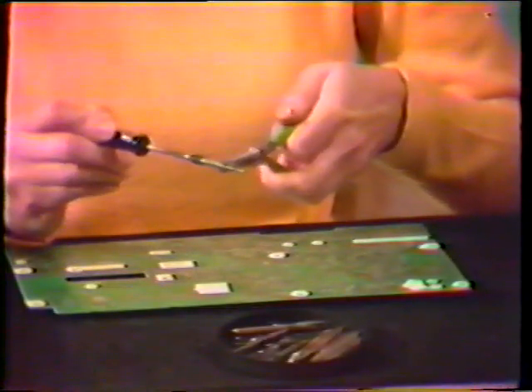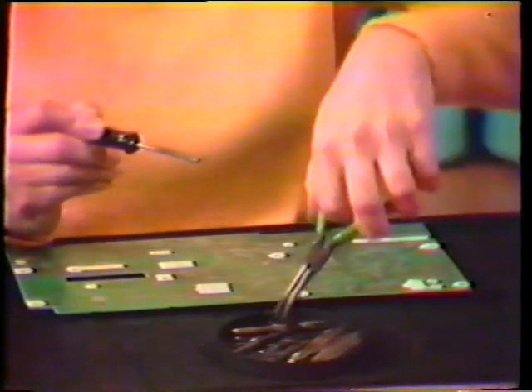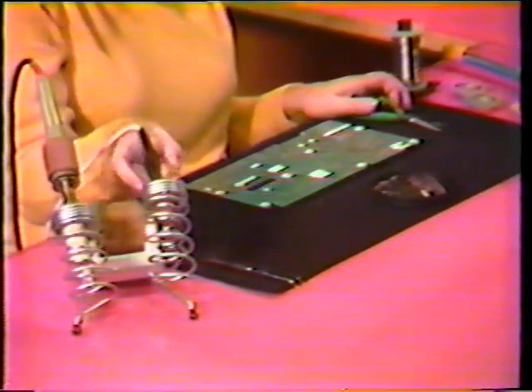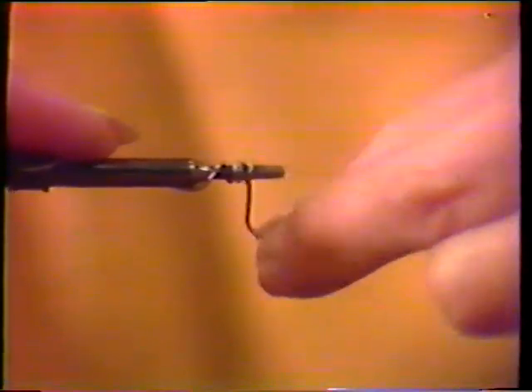But restoration can be done in a short time, either by the operator or someone designated in the assembly area. The recommended procedure is to remove the soldering tip from the hot iron and let it cool. Then, with a piece of 100 grit emery cloth obtainable from central stores, remove the scaly oxides and polish the tip. Next, wrap rosin core solder around the cleaned surface as in normal tinning.